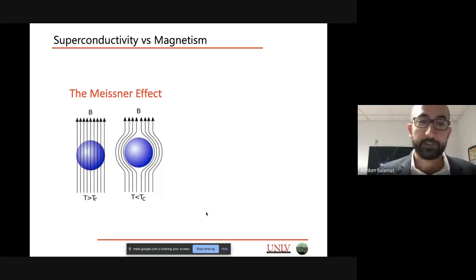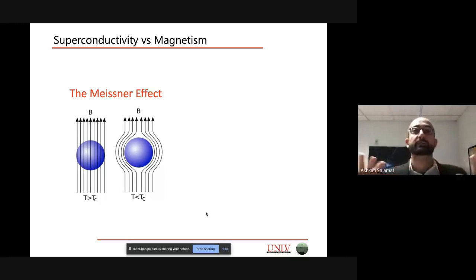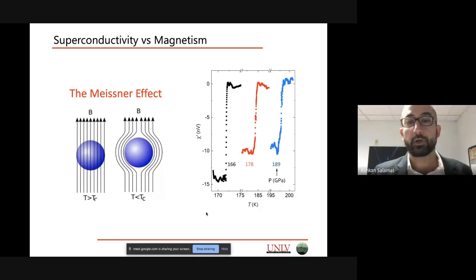Now, in addition to zero electrical resistance, the real signature for a superconductor is something called the Meissner effect. Superconductors repel magnetic fields. In fact, superconductivity and magnetism hate each other. As you pass a magnetic field across the superconductor, it uniformly dispels all of the field. Because of this characteristic of this material, we can do something called AC magnetic susceptibility, where we can show the diamagnetic response of the material.